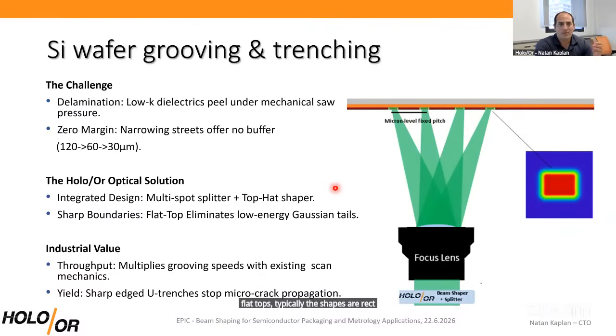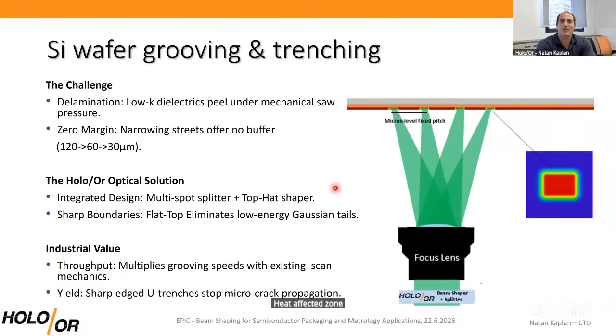Typically, we make such in UV or green wavelengths, but can be in any wavelength that is process appropriate. It creates an array of flat tops. Typically, the shapes are rectangles, few tens of microns in the long dimension. And these shapes are then scanned over the surface to give you higher throughput, because you're multiplying grooving speed, and better yield because of the sharp edges. There is much less delamination. The area that is affected, the heat affected zone and the delamination zone, is much less.